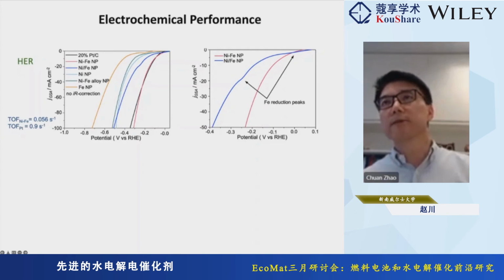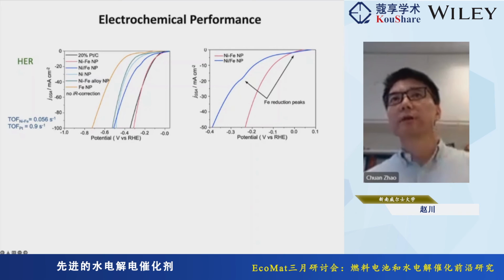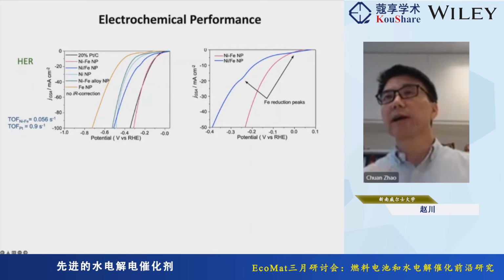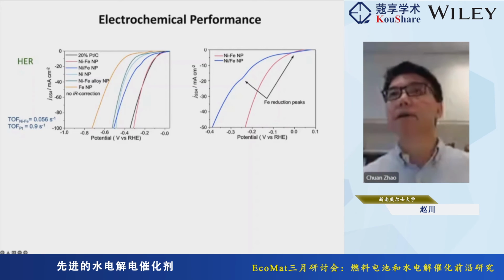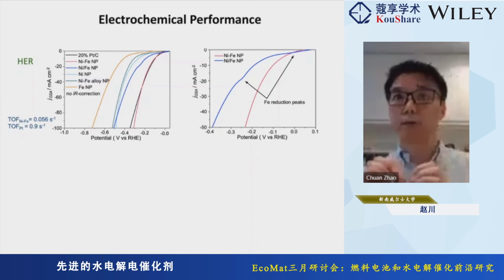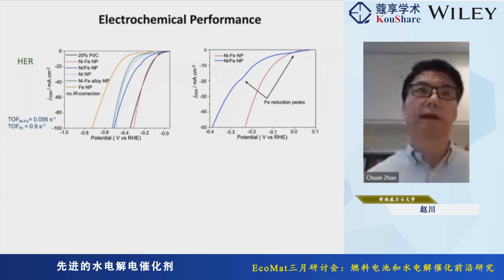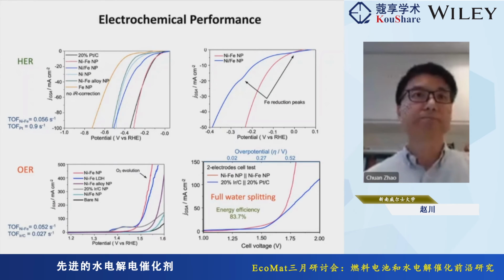We can also see that with a conventional nickel iron based electrode, when you do HER, you often see this reduction peak of iron. But in our catalyst, we don't really see that peak, suggesting the active sites are not formed in situ, but are already on the catalyst when the reaction starts.